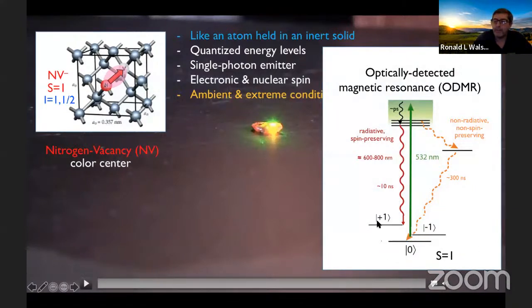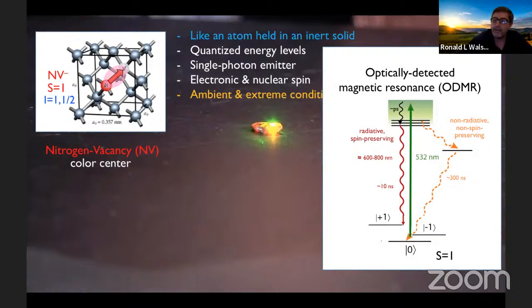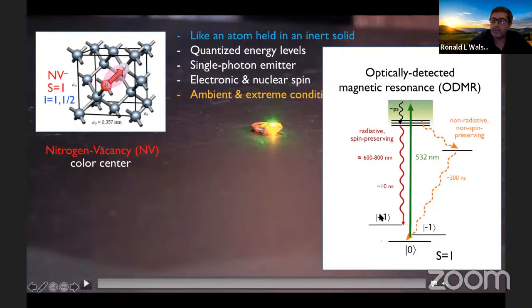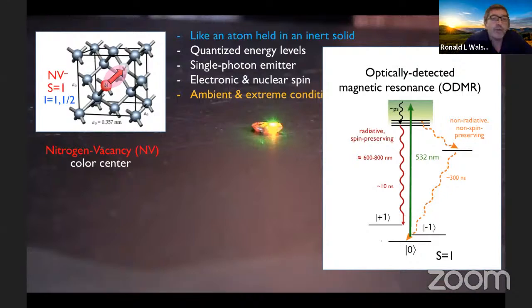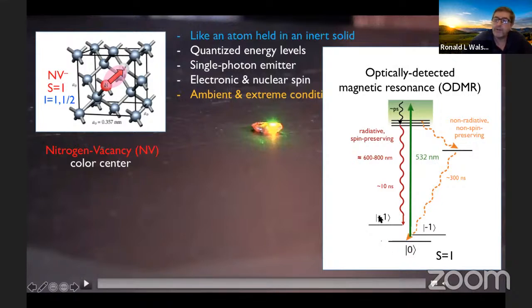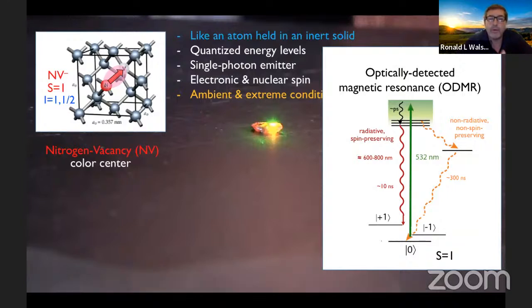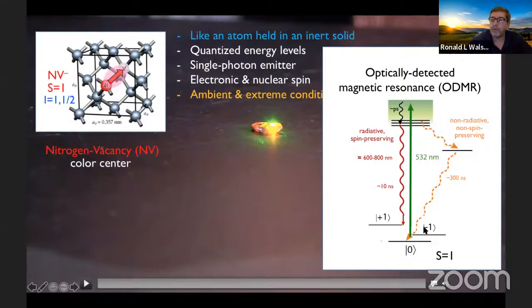At the bottom of this diagram, you see 3 energy levels. This is the electronic ground state. These are the spin levels, the electronic spin levels, the m_s equals 0 level, and the m_s equals plus and minus 1 levels. I show the plus and minus 1 levels offset from each other as if they would be Zeeman shifted by a magnetic field. But there's also a zero field splitting. Even in the absence of a magnetic field, the 0 and plus and minus 1 levels are offset by about 3 gigahertz due to the magnetic dipole interactions between the 2 electrons that make up the NV electronic states, the leading order electronic states. So those are the ground electronic states. There is also the nuclear spin hyperfine structure, not shown here.